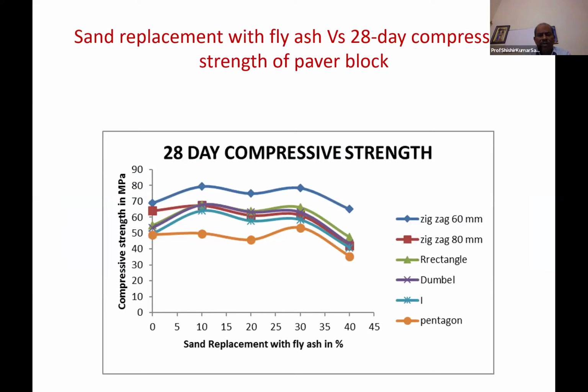All of the paver blocks behave in the same manner. So at least 10% we can conveniently replace, or more, keeping the same strength. 10% is showing the optimum, meaning more strength, but the others are showing similar strength too. So 20%, up to 30%, we can also go and get similar strength.